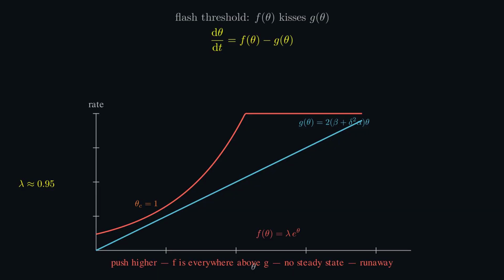And then they kiss. Tangentially. One single point of contact. That is the flash threshold. Push a hair higher and the curves separate. F is everywhere above G. No more crossing, no more steady state. d theta dt stays positive. The temperature does not stop.